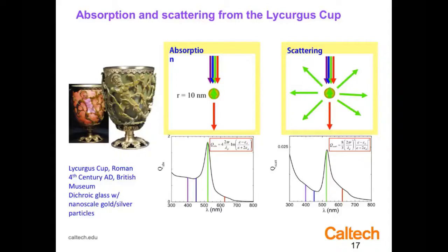I see a resonant extinction in the green from the surface plasmons, and I see the red glow coming from the transmission through the cup, through the glass layer of the cup. In the case of viewing it from white light from the outside, it looks primarily green because red light is transmitted. And the scattering cross-section is actually stronger for these particles than the absorption cross-section. So from the outside, then the scattered light is predominantly green, which is why you see this characteristic color.